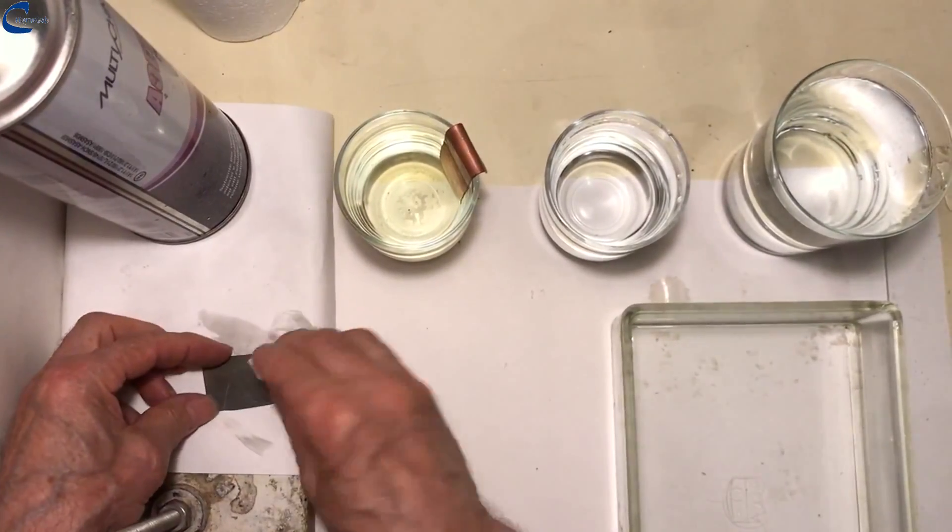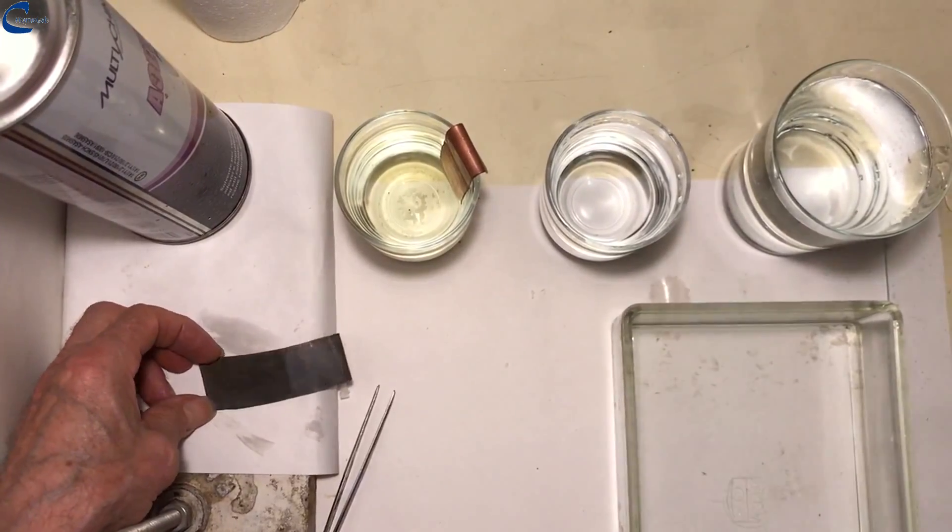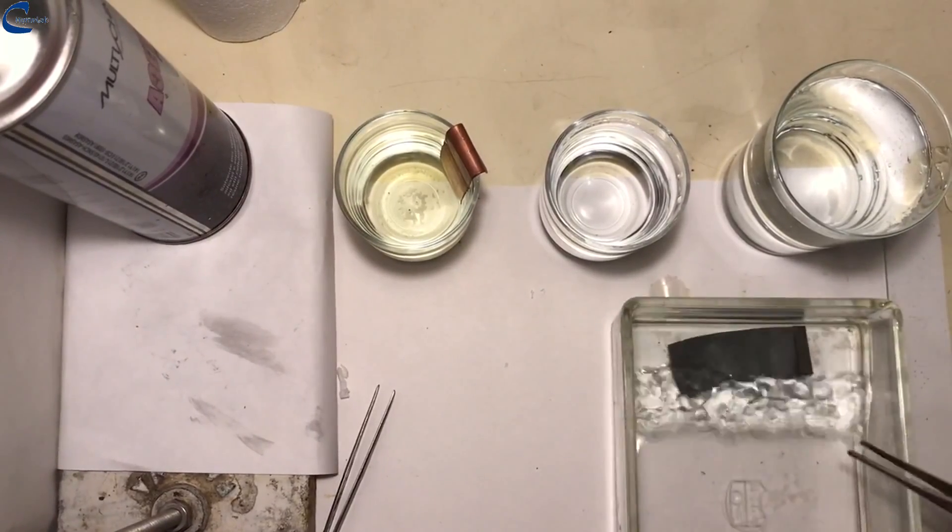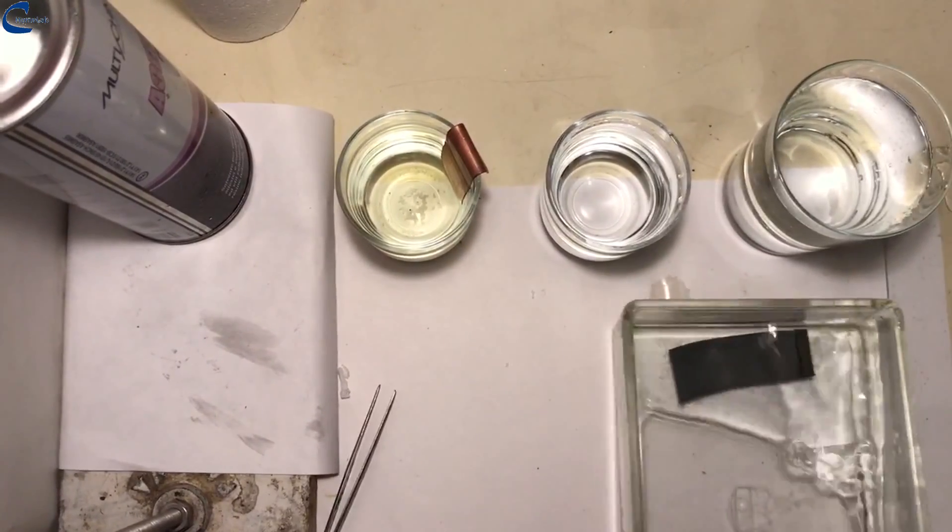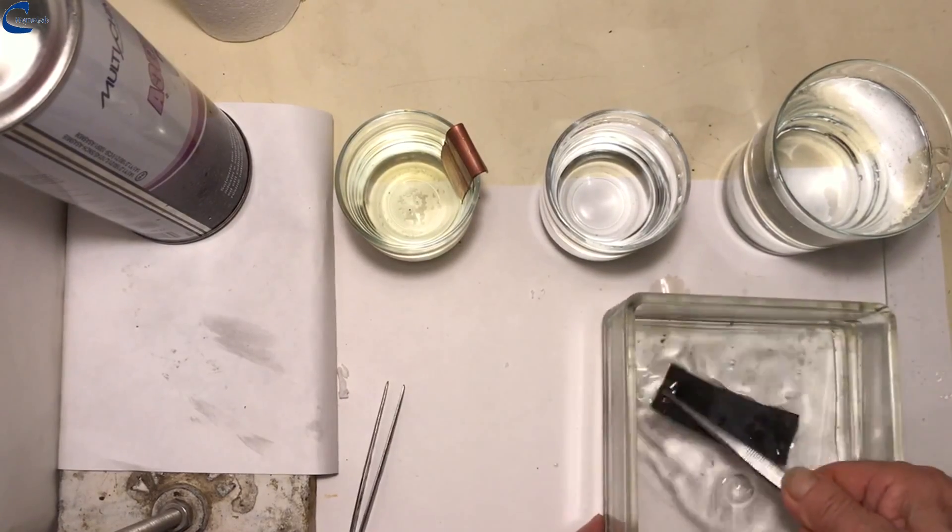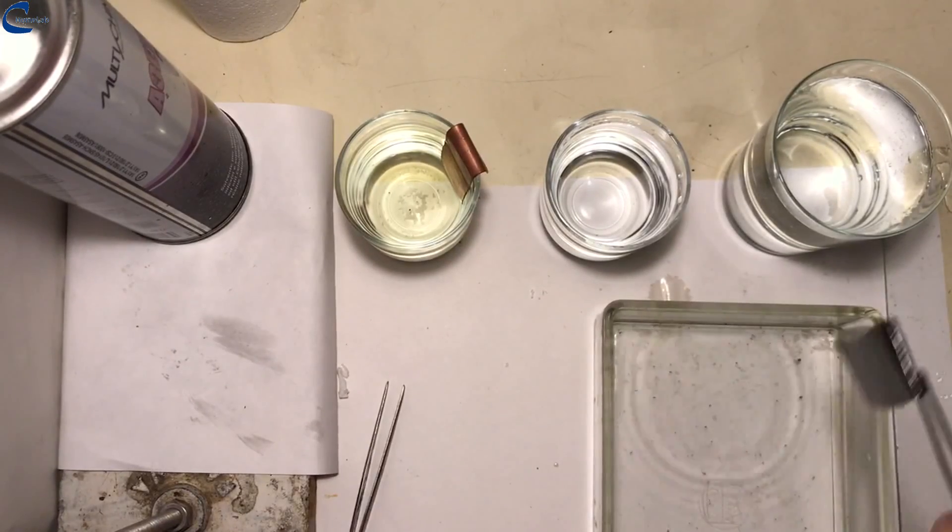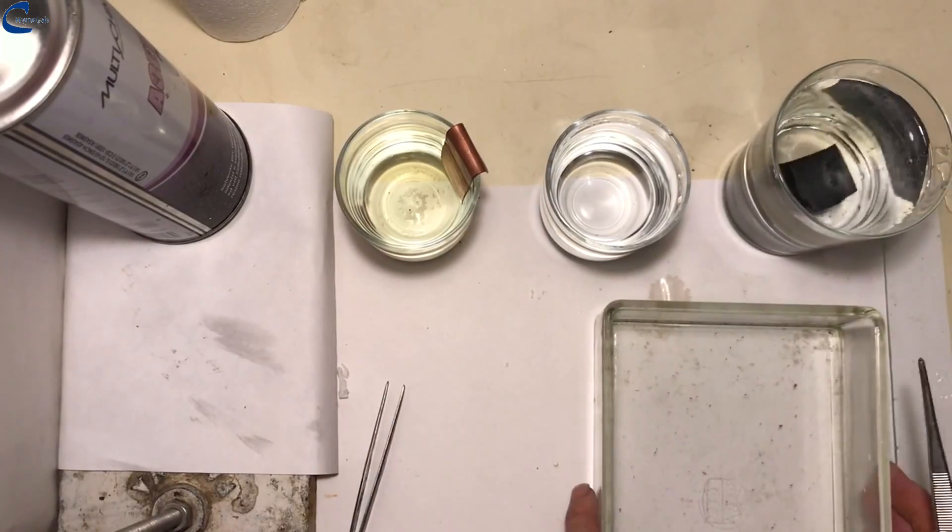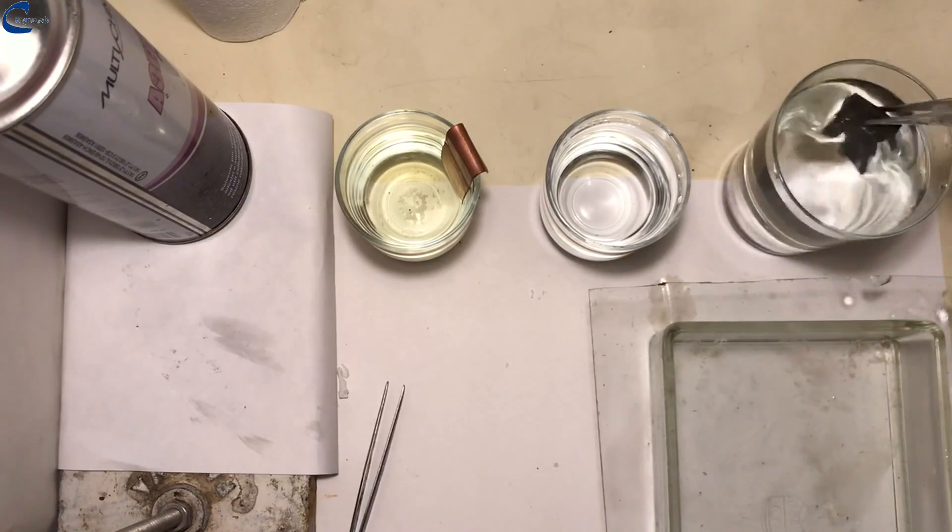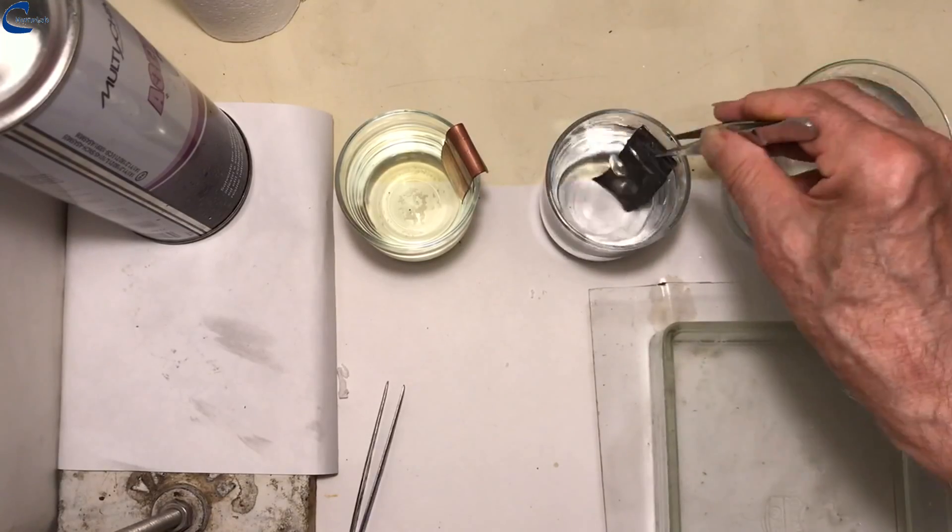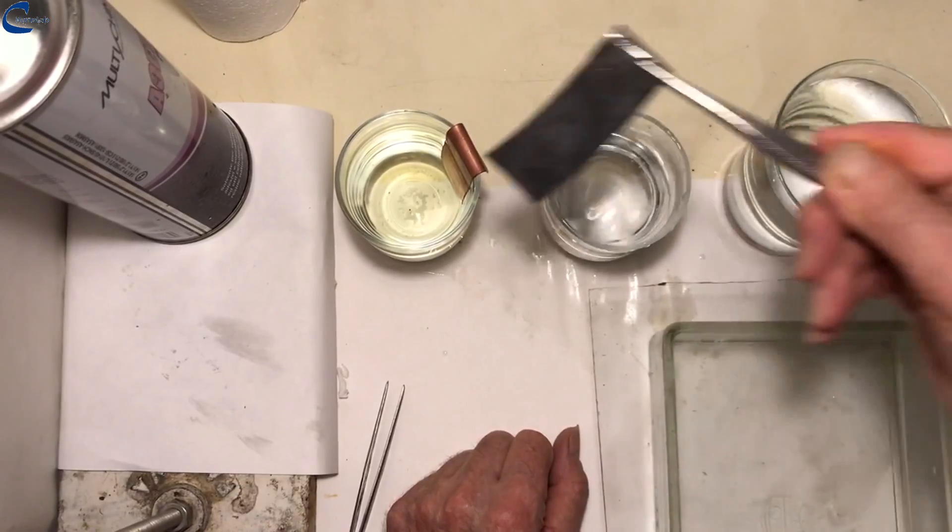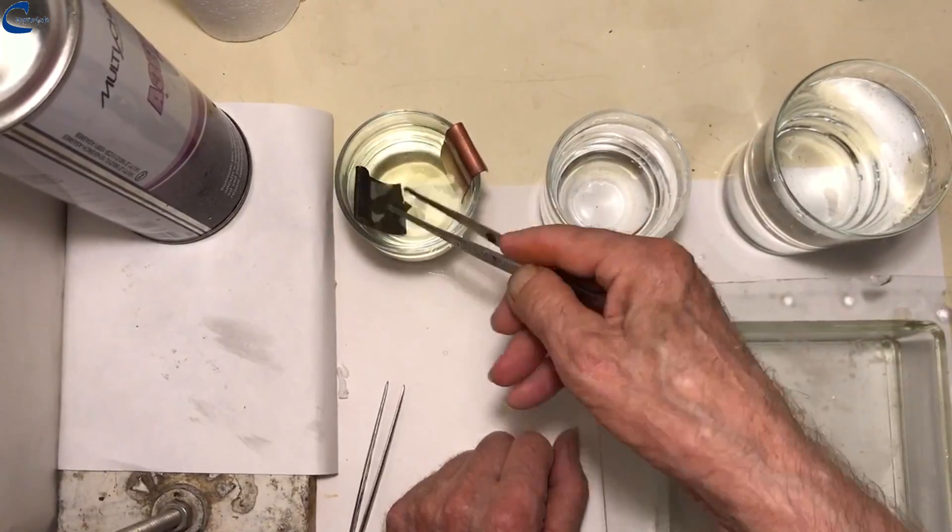It is then soaked in a solution of 4.5-5% sodium hypochlorite, normal bleach. And then we move onto the lead electrode who undergoes the same treatment and is dipped in the same glass of bleach. The electrodes remain immersed in sodium hypochlorite for 48 hours.